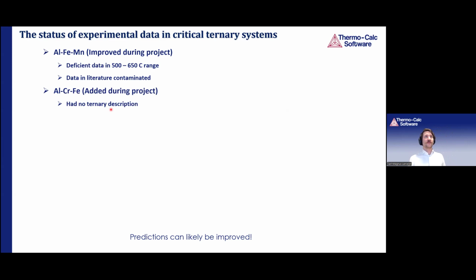Aluminum chromium iron was actually not described before because there was limited data available, but now there was new data, and we were able to assess this ternary system and put it in a database, which of course will be very important for predictions using chromium and iron based intermetallic alloys, intermetallic phases.